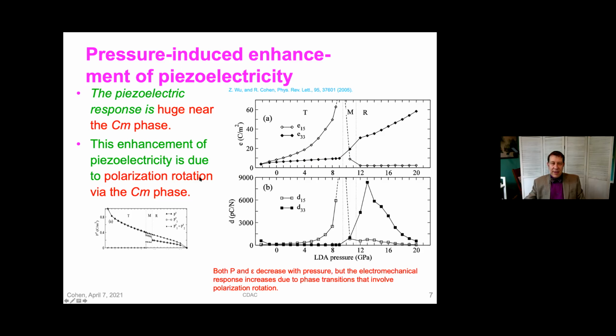And this led to a better understanding of the whole nature of high coupling ferroelectricity, which I'm really not going to dwell on today. But this idea of polarization rotation, that what's happening in these transition regions is the polarization is rotating from the 001 direction, like a cube axis, towards the 111 direction, which is a cube diagonal. And in the middle, it's monoclinic.